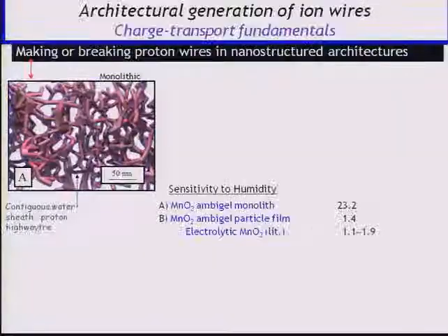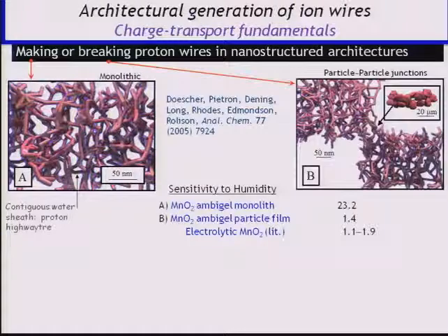So we can make or break the proton wire based on what we do with the size of that ambigel. And when we're monolithic, we chemisorb water from the vapor phase. Ultimately, we'll build up a sheath of water around the scaffold of the oxide, and that's why it's just running back and forth with impunity. But you break it by introducing impedance junctions. It may be moving quite rapidly through here, but it still has to hand off particle to particle.